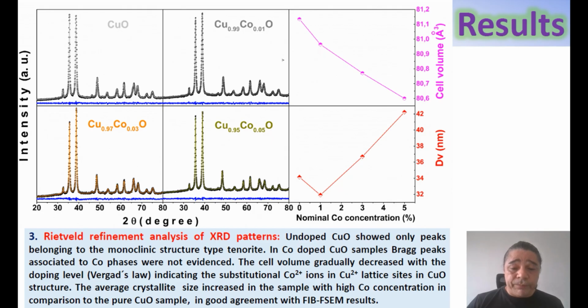XRD of the undoped copper oxide sample showed only peaks belonging to the monoclinic structure tenorite. In cobalt doped copper oxide samples, the peaks associated to cobalt phases were not detected. The cell volume gradually decreased with the doping level, indicating substitution of cobalt 2 plus for copper 2 plus into the lattice site of the copper oxide structure.